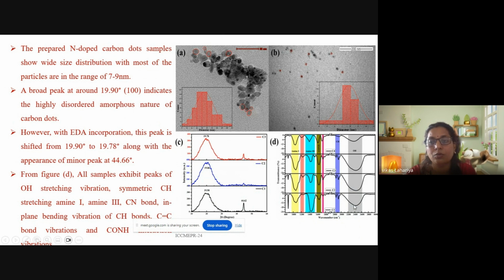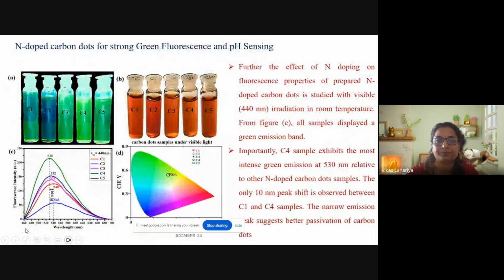various functional groups, like the OH stretching vibrations, CH stretching vibrations, and the amine group, which is due to the presence of the EDA, can be seen. The bonding with the carbon atom is represented by the CN bond stretching, bending or in-plane bending vibrations, and the carboxylic groups are present here.